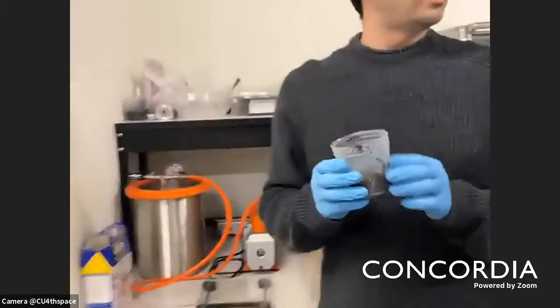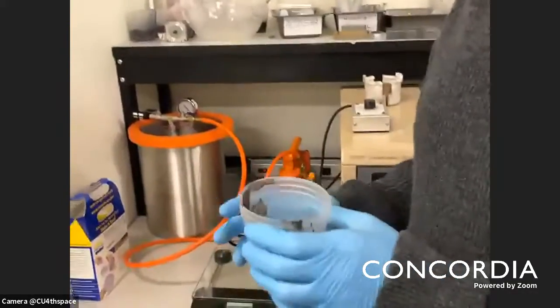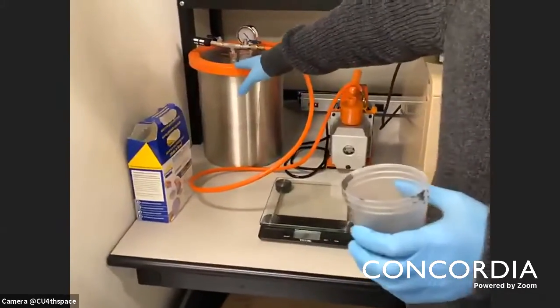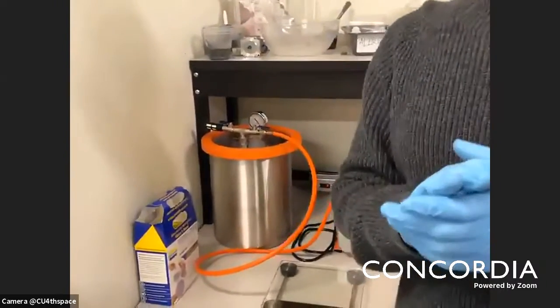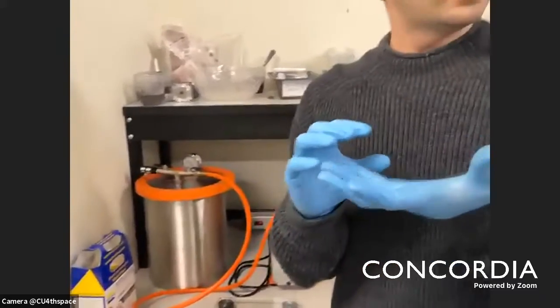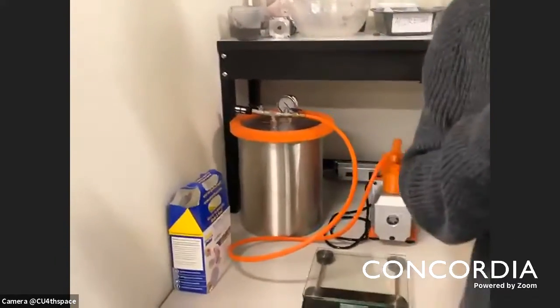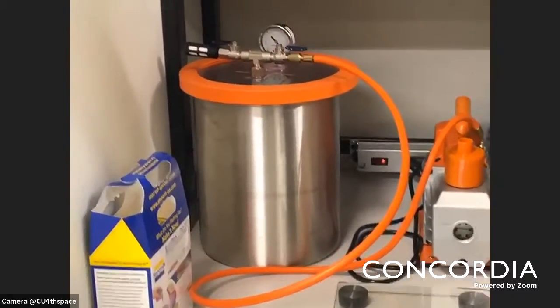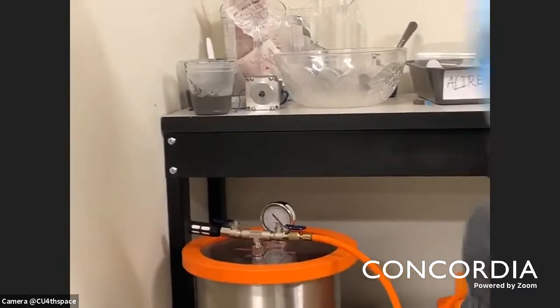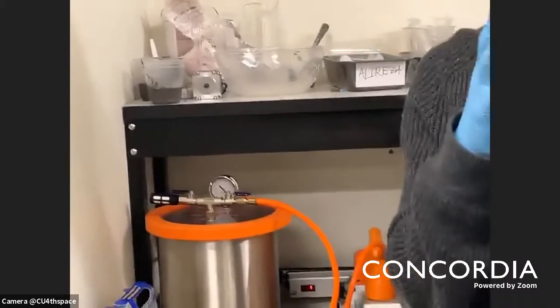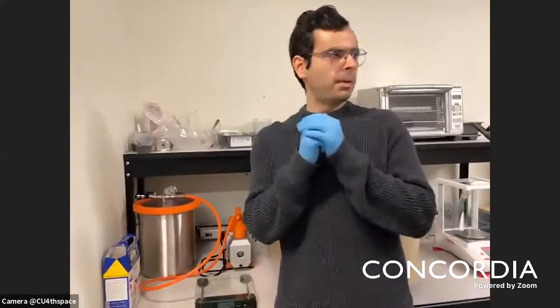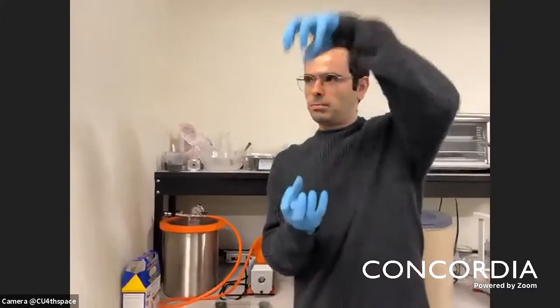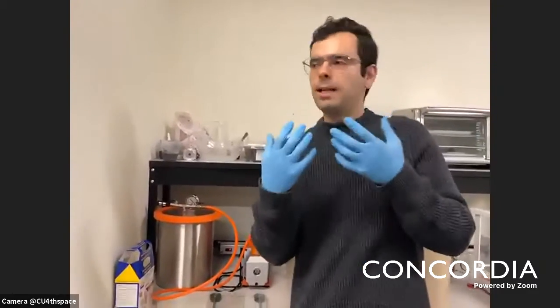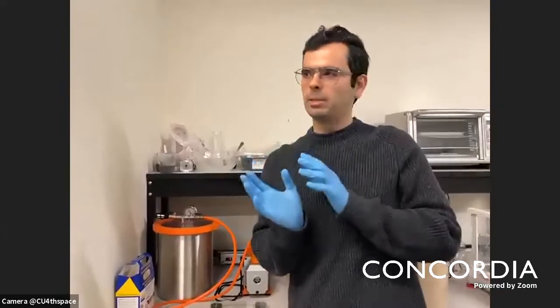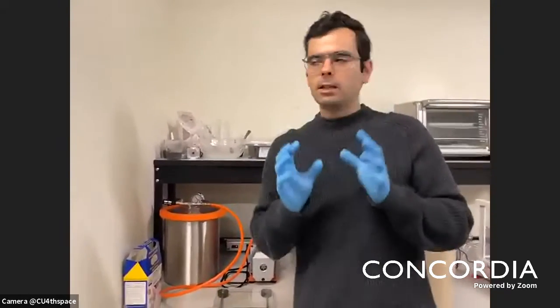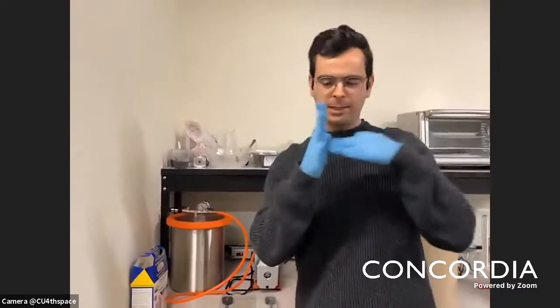For example, when you mix the iron and silicone inside a mold and put the mold inside this vacuum chamber, the air bubbles will be removed. Then if we pour the mixture in a specific mold, after 24 hours you will have isotropic MRE, which means that the iron powder is randomly distributed in the matrix, so the material properties are identical in any direction. However, if you put the mold inside that magnet, we can permanently align chains of iron particles inside the matrix. So once the material is fabricated, we call it aligned MRE, structured MRE, or anisotropic MRE. This type of material has different magnetic responses perpendicular to the chain and in the direction of the chain.